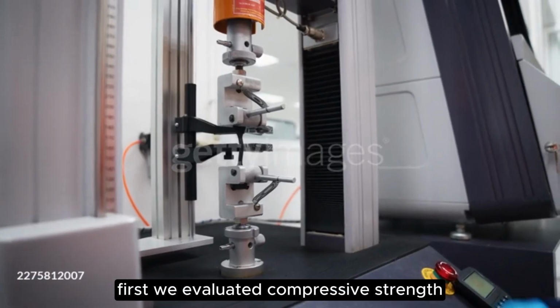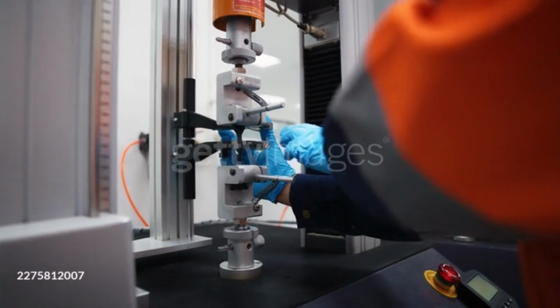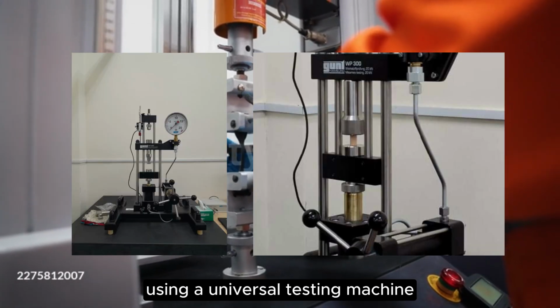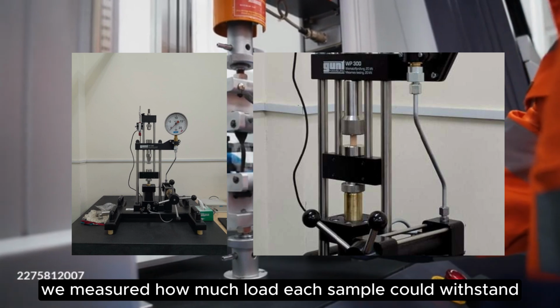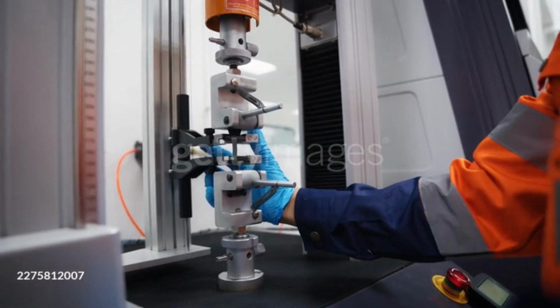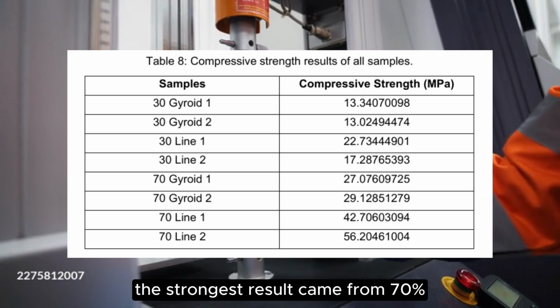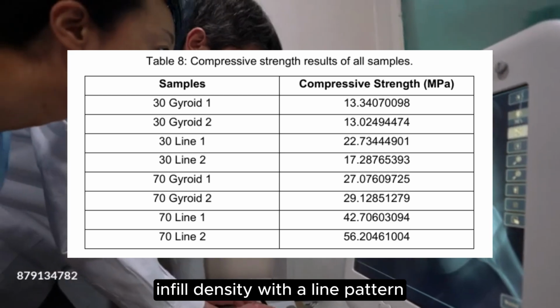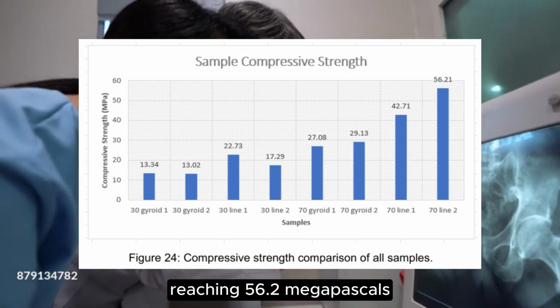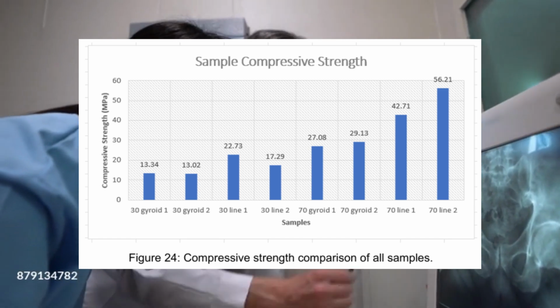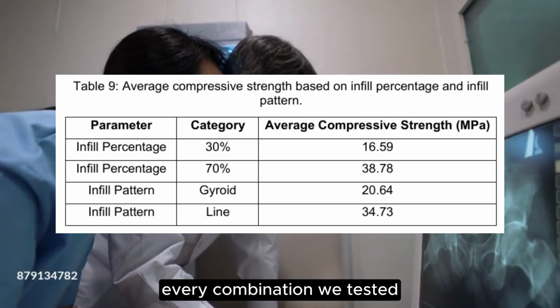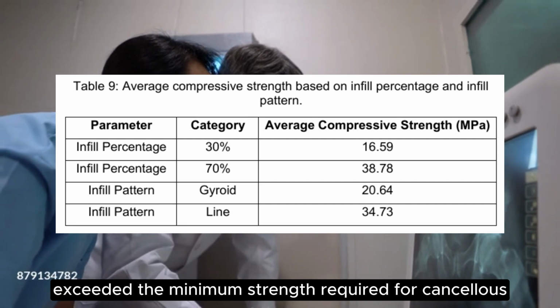First, we evaluated compressive strength. Using a universal testing machine, we measured how much load each sample could withstand before failure. The strongest result came from 70% infill density with a line pattern, reaching 56.2 megapascals. Every combination we tested exceeded the minimum strength required for cancellous bone.